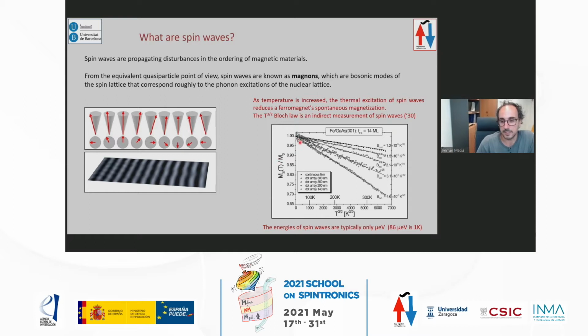Here in this graph, what I show is the first, let's say, evidence. This is an indirect evidence of the existence of spin waves, and that was about 100 years ago. This measurement is showing the magnetic moment, the saturation magnetization of a magnetic material as a function of temperature. And what was seen is that there's a law showing that when you lower temperature, the magnetic moment increases. I prefer to say that when you increase temperature, you lower magnetization. This is because you thermally excite magnetization dynamics, spin waves, and these spin waves are just lowering the magnetic moment. This is called the Bloch law, and the magnetization goes as the temperature to the 3/2.